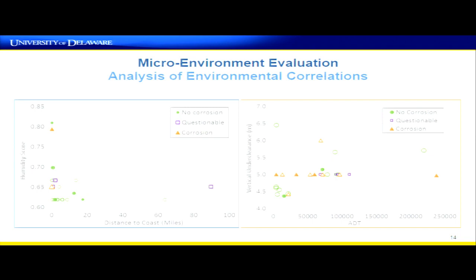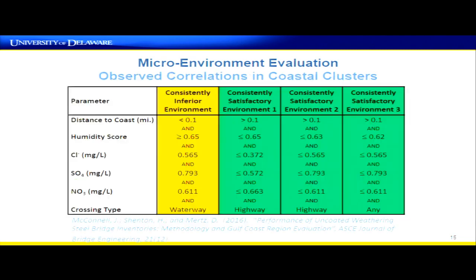On the right is the same type of data, but for bridges over roadways treated with de-icing agents. And here we see the main parameters were vertical underclearance and the ADT of the highway underneath the bridge. So this is really a direct measure of how much chloride is getting onto the bridge from the salt spray. Again, there are some trends here, but there are also outliers and not everything's grouping together. And that has to do with how much snowfall is at the location, how much atmospheric chloride is in the air at the location. So again, if we could have a four-dimensional graph, those orange data points and the green data points would separate themselves into different spaces.